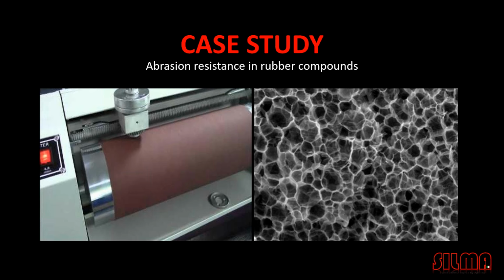You slip completely. Also, recently most of the shoe producers want very exotic or colorful shoes. And instead of using a colored rubber, they apply color on the surface. And in this case, the presence of the wrong type of silicone additive, or too much silicone additive, makes it impossible to apply glue or color on top of the rubber. So the point is too much silicone additive can affect the adhesion properties of paints, when you want to make adhesion with the lead or with other parts of the shoes, or it is impossible to color, because when you apply some paint on the rubber, it will be easily debonded.